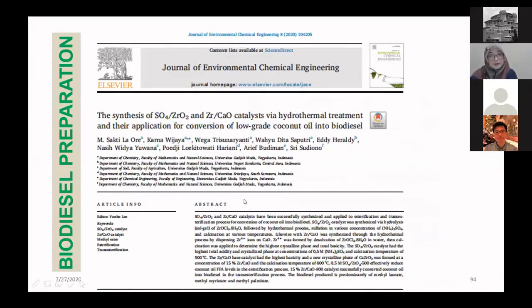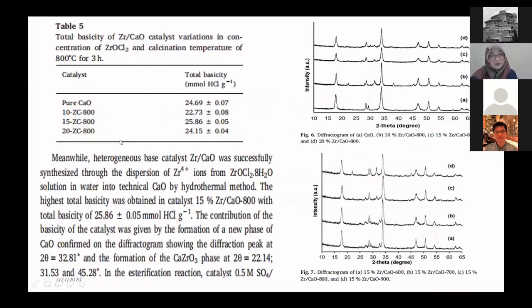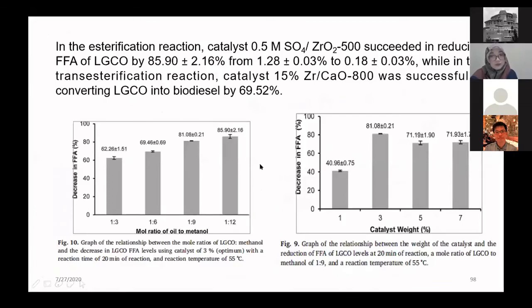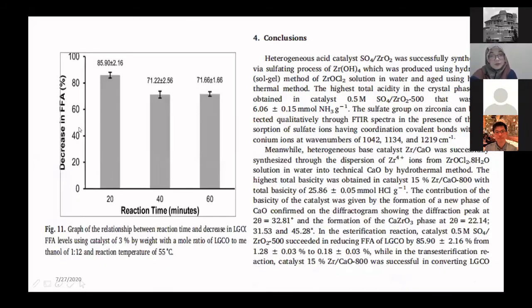Increasing the mole ratio will decrease the free fatty acid if you use sulfated zirconia. And the catalyst weight will also decrease the free fatty acid in the vegetable oils. This one shows the decrease of free fatty acid in the material versus reaction time.